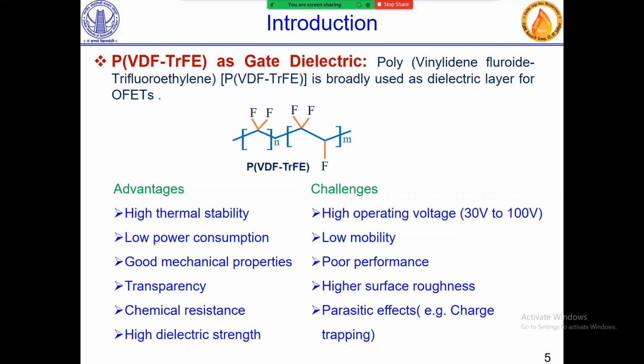There are also challenges associated with PVDF-TrFE based OFET like high operating voltage of 30 to 100 volt, low mobility, poor performance, higher surface roughness, parasitic effect, and charge trapping. Due to higher surface roughness, charge trapping takes place, which leads to high operating voltage from 30 to 100 volt.